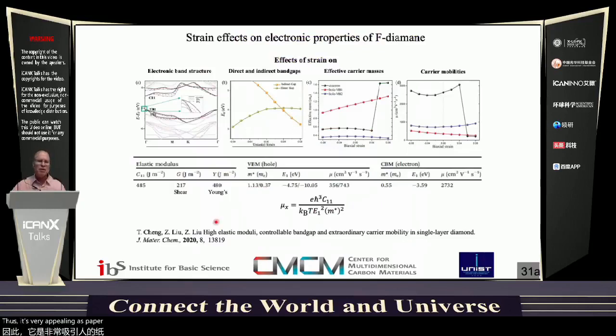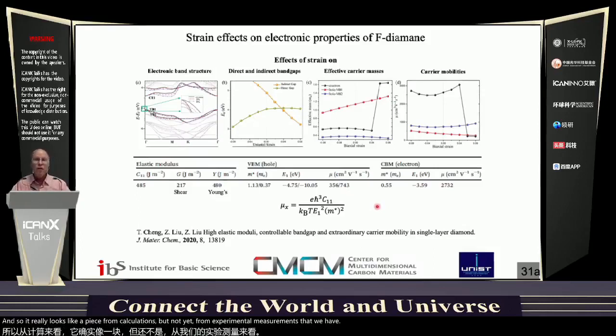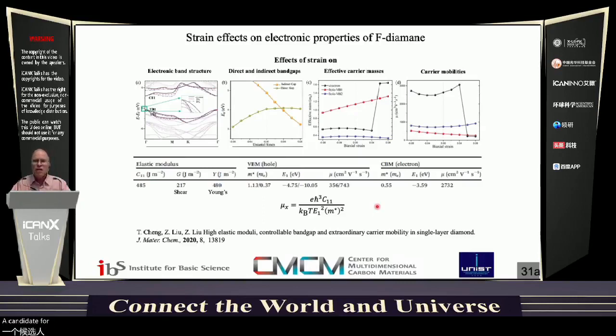This paper from Zhang Fan Lu and colleagues was recently published. They find in their calculations of the F-diamane a very high electron mobility. Electron mobility values can be up around 2700 or near 1000 for electrons and holes. And so it really looks like, at least from calculations, but not yet from experimental measurements, that we have potentially a new candidate for various sorts of devices in this F-diamane.